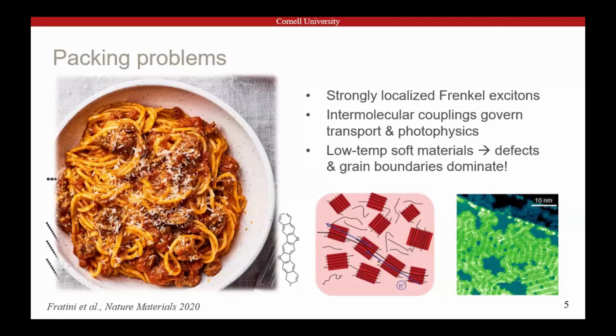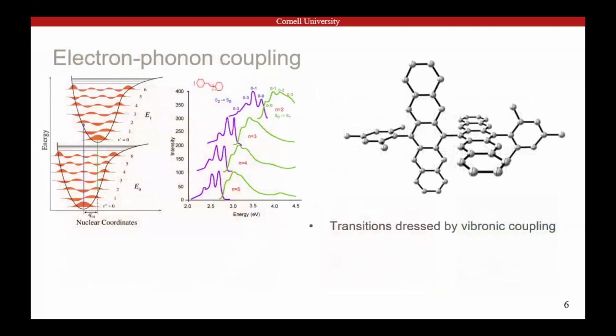So you have to understand and work with not only these well-defined crystalline regions, but also the boundaries in between them. And these grain boundaries, the defects, turn out to have a huge impact on the performance of organic materials in the solid state. And this isn't just going to apply to charge transport. This regime is a useful reminder that the molecules that we put in an organic film have a very wide range of environments. So this is going to affect not just how they couple to their neighbors, but their energetic structure, the vibrations that they have, the things that they can do. So we have this terrible disorder that we cannot get away from because the materials are soft. And that's never going to change.